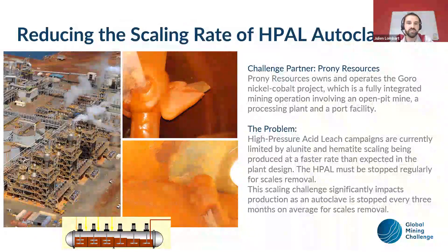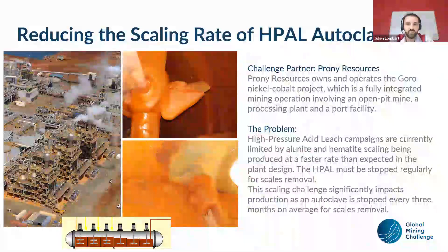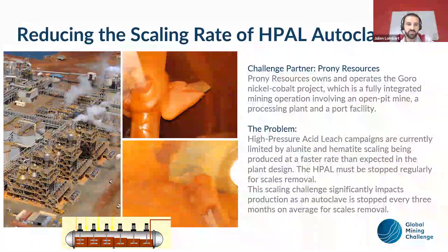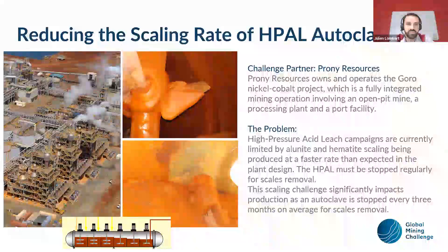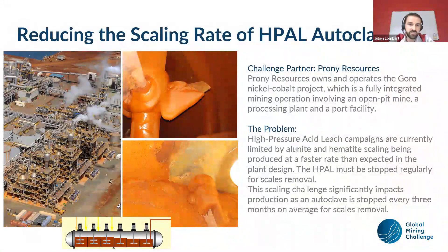It reduces a lot the residence time and agitator efficiency. We are trying to better understand what happens with these scales because in the plant design it was not forecast to be that important. We have a different ore compared to what we should have had according to the design, and that explains a lot why we have this scaling.